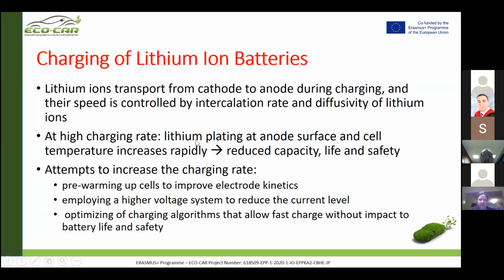So-called lithium plating. So you get lithium directly on the electrode, and that's not the desired place. You want your lithium intercalated in your materials, the oxides and the carbon. So this high charging rate can induce reduced capacity, reduced life, and of course reduced safety, because the cell is getting very hot, and there's a risk of catching fire, of explosion.